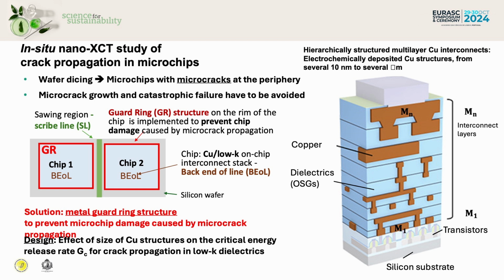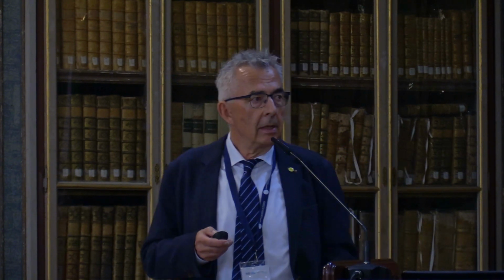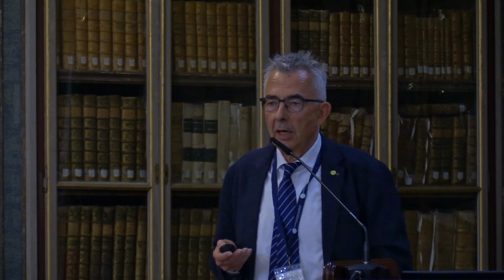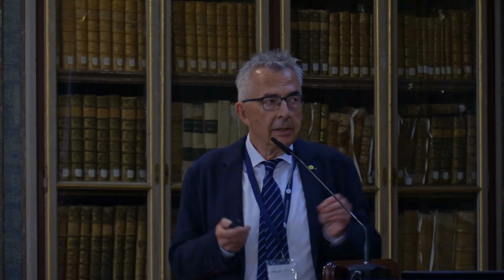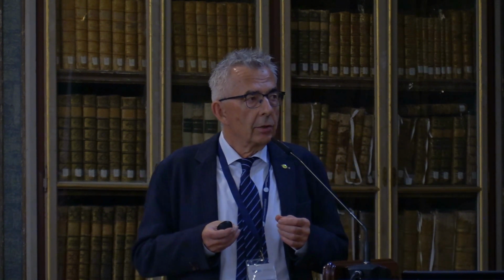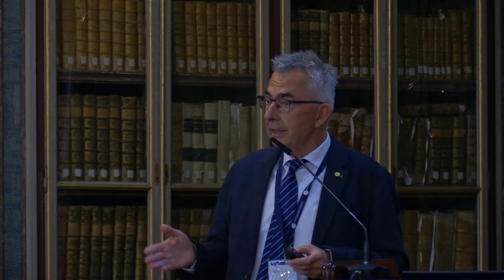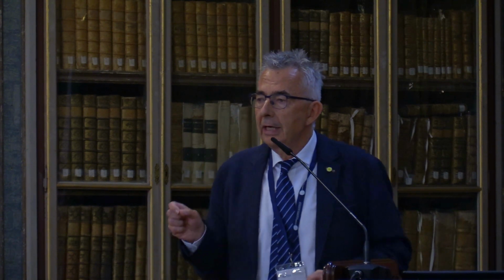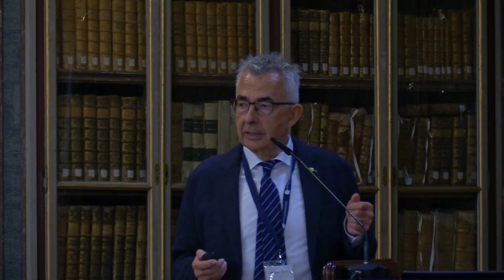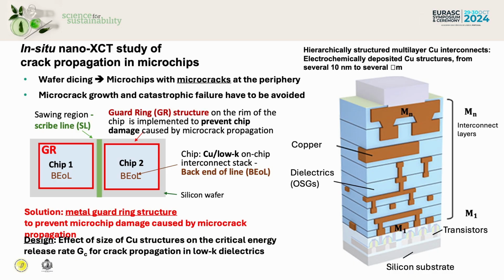Here you see on the right-hand side a schematic cross-section through a microchip. At the bottom, there are these 1 billion or so transistors, but then on top there are 10, 12, or 15 layers of copper interconnects. This is the design. And these copper interconnects are isolated by dielectrics. So if you have a 300 millimeter wafer and you want to select the individual dies, the chips, then you have to do a dicing process. And during this process today, it's not possible to avoid microcracks at the periphery of the microchips. And there's a high risk, and this really happens, that cracks propagate into the active area of the chip, and then you have a catastrophic failure.